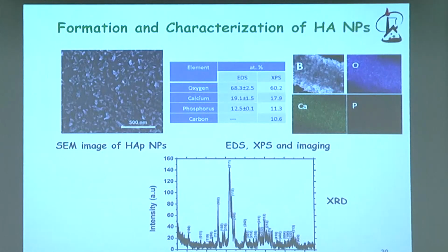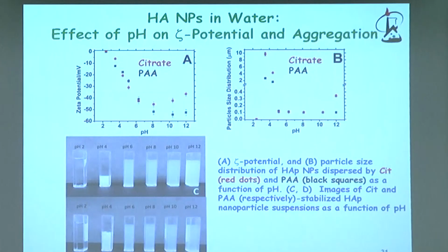I have everything here. I'm not going to go into details, so we synthesize, we have very good characterization of the hydroxyapatite nanoparticles, and then you can see here very nicely, first of all, in solution, what happens to these nanoparticles that are stabilized with carboxylic acid. As you go to lower pH, they simply precipitate.